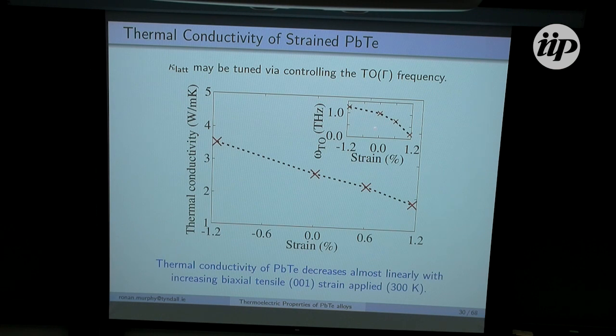And then, again, as I've just been saying, by softening that TO mode frequency at the gamma point, you reduce the lattice thermal conductivity. So it just further reinforces the point I've said a few times now, that you can push lead telluride away from or closer to the phase transition, and by controlling that TO mode frequency at the gamma point, you can alter the thermal conductivity as you like.